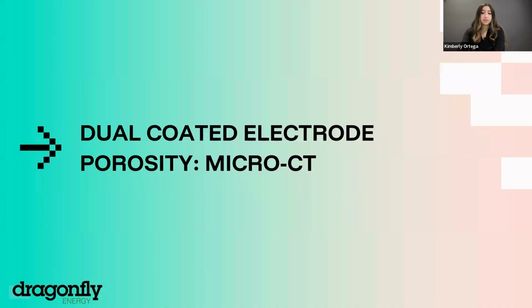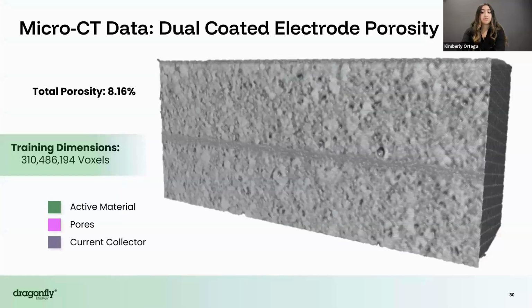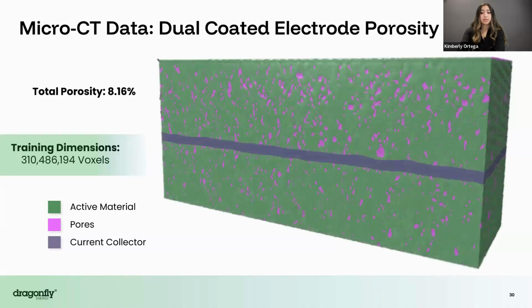We also looked at X-ray micro-CT data using the UniTOM HR system. This technique is non-destructive and it's ideal for capturing larger volumes, which makes it well suited for bulk analysis. For this imaging technique, we focused on total porosity, which was calculated at 8.16%. So it's currently not as accurate as our other methods, and the internal and external pores were not classified as they were not clearly distinguishable at this resolution. So although micro-CT can't yet capture pore accessibility or tortuosity at this scale, it's still a valuable insight for evaluating uniformity, large area defects, and performing non-destructive quality checks.